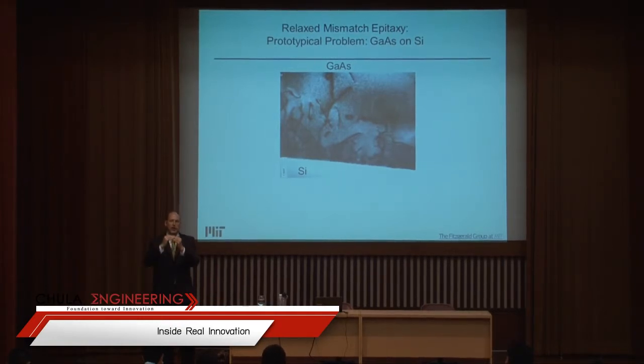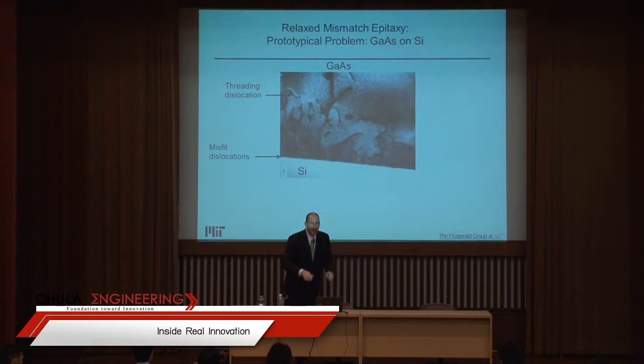And so what happens, of course, at what's called the critical thickness, you introduce dislocations which have energy, but they come in and relieve energy, and you have this problem, right? So these dislocations act as recombination centers, which means that if you try to make solar cells, lasers, or anything that needs minority carrier lifetime, and even for a majority carrier device, it's too short. So basically, it's useless material, right? So very fundamental problem. The terminology is threading dislocation and misfit dislocation.